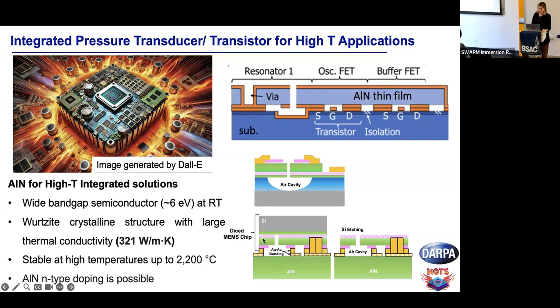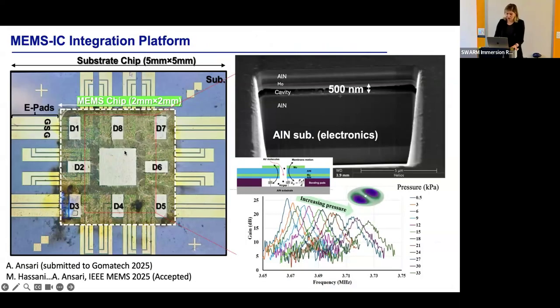So I'm going to show you a way that you can bond with either metal layers or other materials to bond the MEMS die, which is sputtered aluminum nitride on silicon, to your aluminum nitride electronics, and then etch away the silicon to form these air cavities or suspended membranes. So just a quick show of what we have done so far. We have our MEMS die on the top, the silicon is removed. So you can see the aluminum nitride, the moly, and then this cavity, which for this particular pressure sensor is very important for us to have a defined cavity depth.